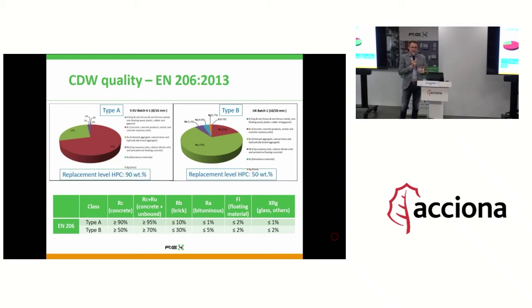And also, when we're working with this, trying to optimize use of CDW with respect to the final properties you want from your concrete. This is the replacement level, for example, for HPC, high performance concrete, we achieved using these two different fractions. So for the high performance concrete, using the aggregates or the CDW to the left, we achieved 90% replacement, whereas we had to lower our ambition levels quite a lot with the one to the right.